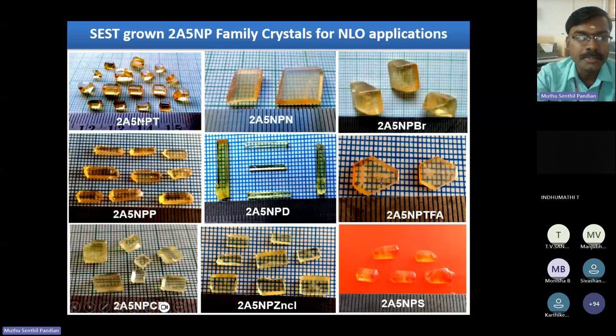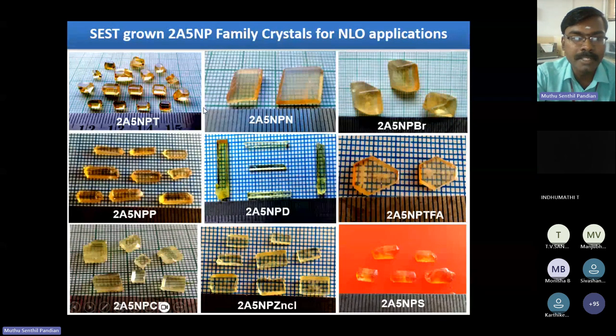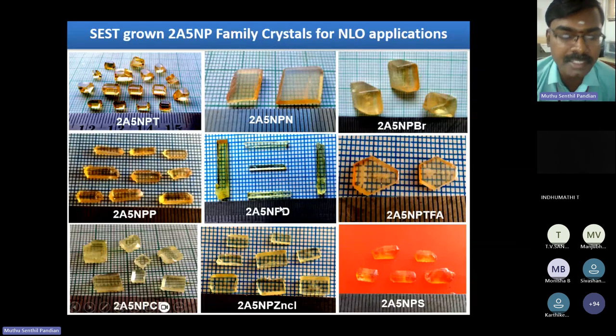optical application. You see, when we grow the crystal by the conventional method in a small size beaker, crystallizer or petri dish, we can only achieve this much size. But from the application point of view, the efficiency of some of the crystals is very high, like this 2-amino 5-nitropyridinium toluene sulfonate crystal, which is 75 times greater than that of the standard reference crystal, KDP, potassium dihydrogen phosphate crystal. But as I mentioned, we cannot use it directly for practical device application because of its very small